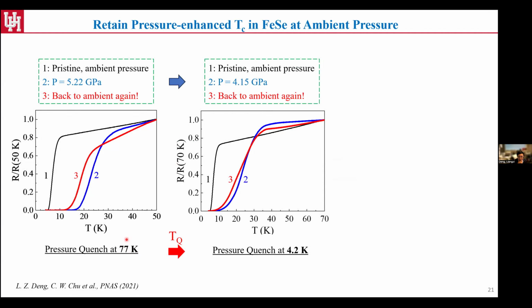So after we cooled the temperature to 4.2 Kelvin and using the new setup we have, we were able to further remove the pressure. And then we did see the TC retained, even though the absolute value of the resistance is not the same, but the onset TC is really close to the high pressure phase that's represented by this blue curve, and the red curve is back to ambient again, as I mentioned above here. So after that, what we care about is how stable it is, right? Regarding time and thermal stability.